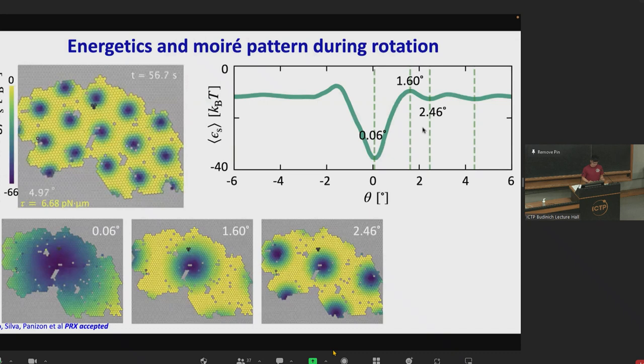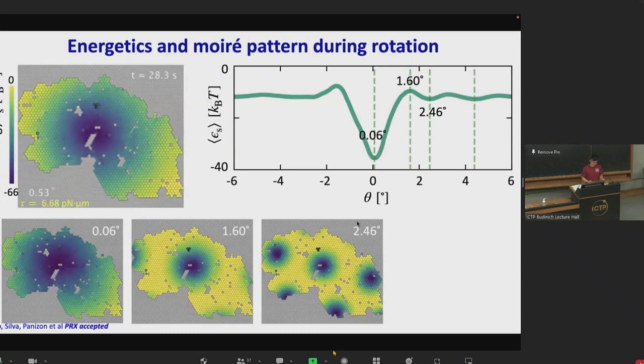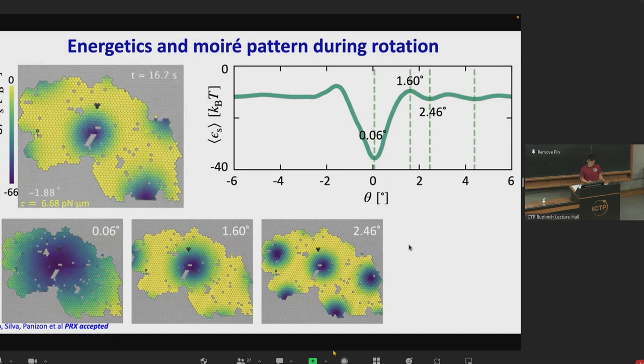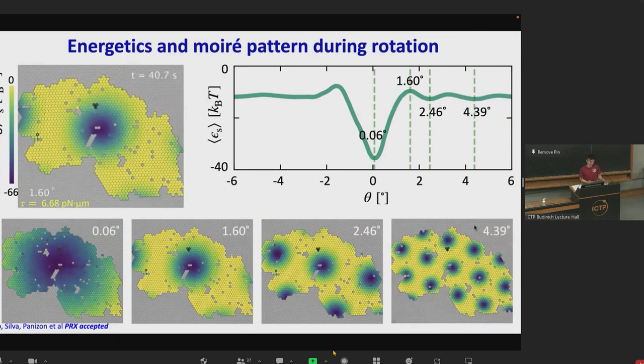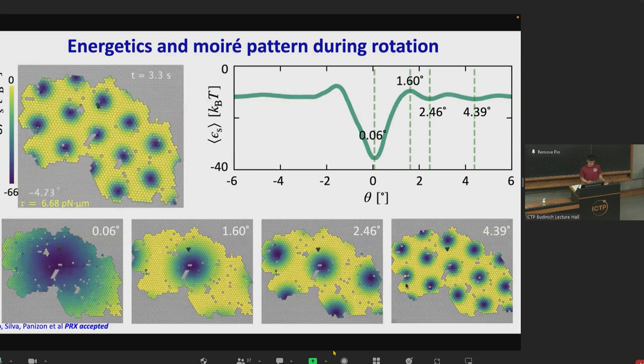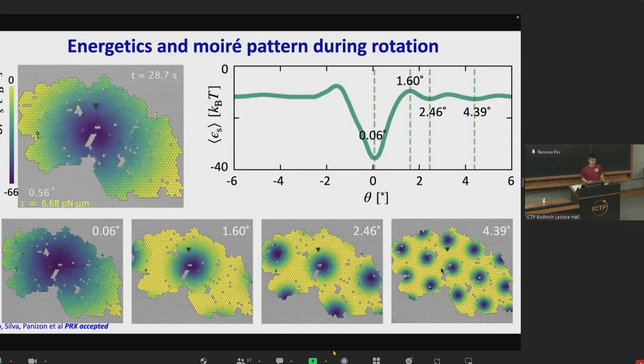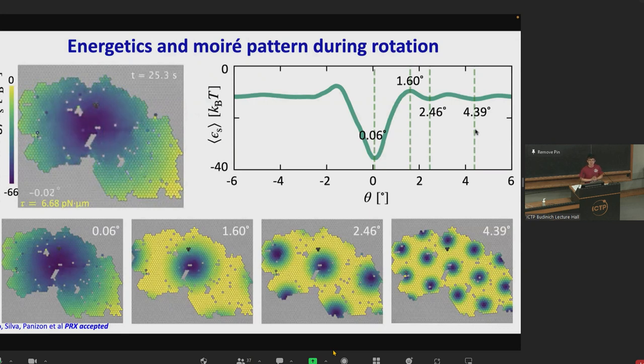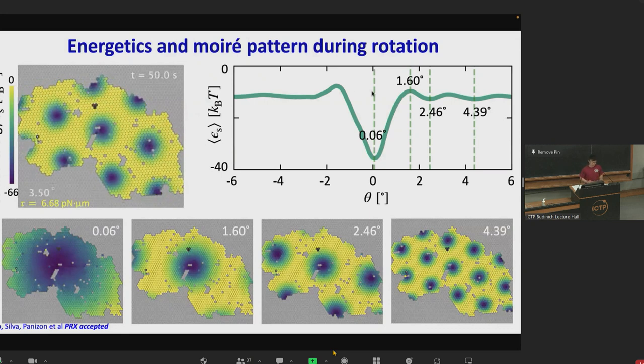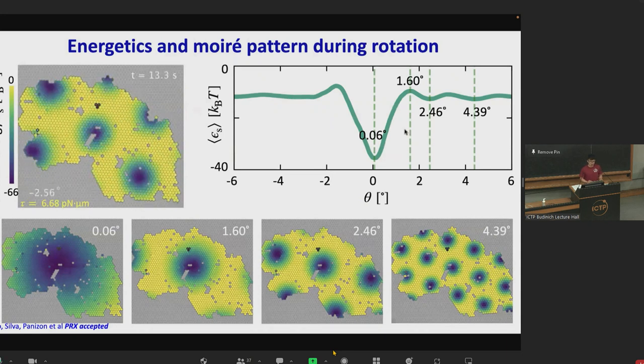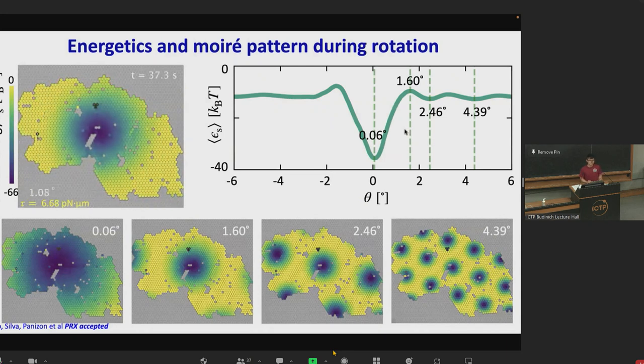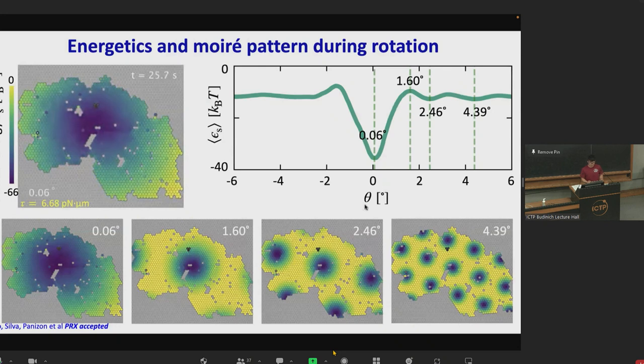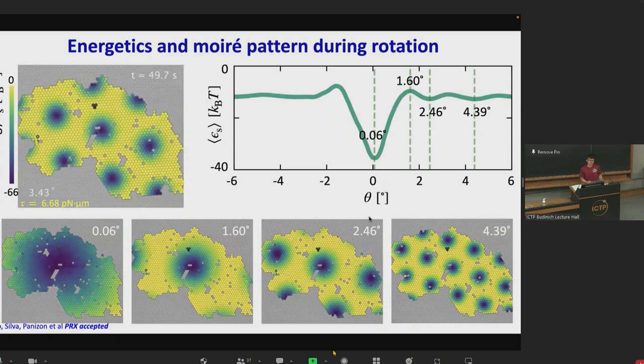When these regions finally enter into the cluster, the potential energy becomes smaller again, because there are now more low-energy moiré spots. The potential energy reaches a minimum at 2.46 degrees when they have just entered inside the inner edge. Similarly, when the cluster rotates 4.39 degrees, a second layer of moiré spots enters the cluster, leading to a second low-energy minimum. The rotational energy profile strongly depends on the cluster's size, shape, and boundary, and how the moiré spots enter the edges during rotational motion, which strongly influences the measured static friction torque.